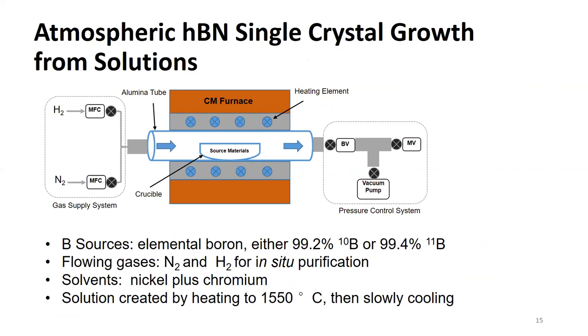Boron is commercially sold isotopically pure, either boron 10 or boron 11, which is how we get the monoisotopic material. So the solvents we use are nickel plus chromium, at a temperature of 1550 Celsius. And it's an open system. We have nitrogen going through here and vacuum pumps to get rid of the oxygen before we start.